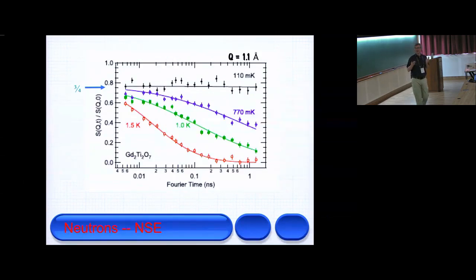Another technique that I use is spin echo, neutron spin echo. And all I want to say here is if you see a nice data set with a normalized scattering function on the y-axis, an ordered magnet, a conventional on-your-fridge magnet, will run across 1. So it's basically saying that your neutron beam doesn't depolarize when it goes through your system and it remains 1. At time equals 0, everything should be 1. The correlations between spins won't change at 0 time. So everything should start here and then relax. So in these systems, we're saying there's something that fastly relaxes and then slowly falls off.